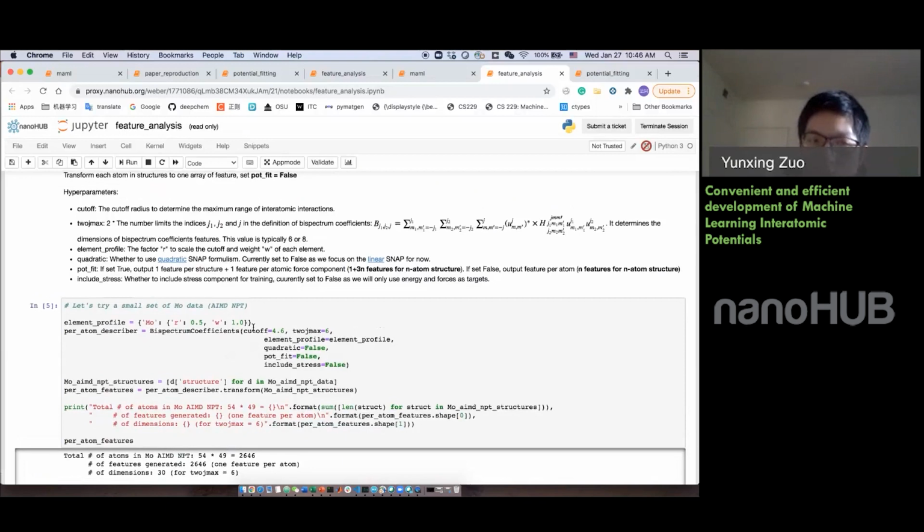And then, what's the difference between the cutoff radius and the cutoff scale factor? In the actual implementation of the LAMMPS SNAP module, these factors scale the cutoff as the scale factor times the cutoff of the center atoms plus the cutoff of the neighbor atoms. If we only train elemental systems, the cutoff for the center atoms and the neighbor atoms are the same. So with the scale here 0.5, we will use 0.5 times cutoff R plus R, which means we have a cutoff radius of R.